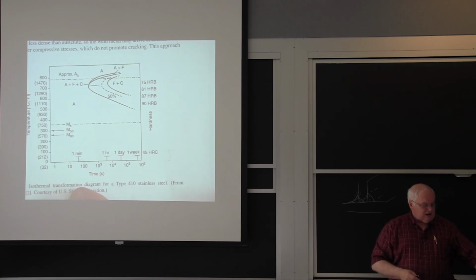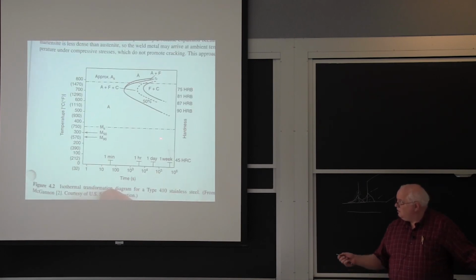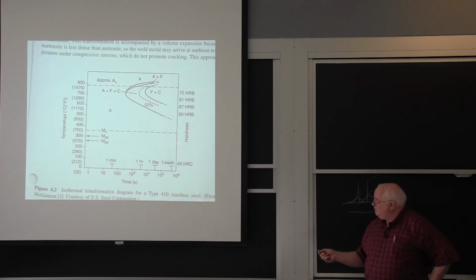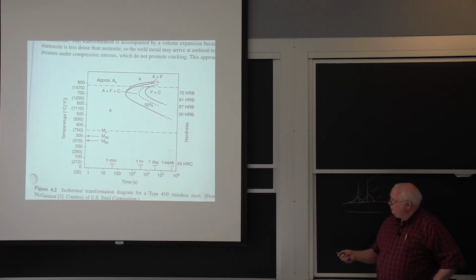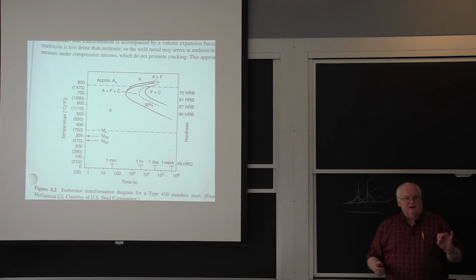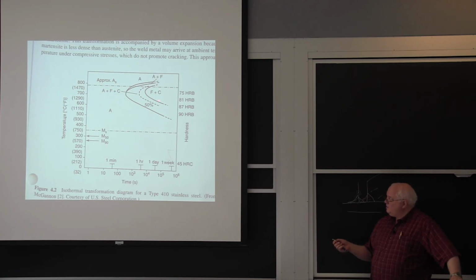There are the ferritic stainless steels, and basically this is the CCT curve for a 410 stainless, which is like 12% chrome. And remember, I was telling you on carbon steels, you had to get past this nose within like 1 second to be able to get martensite and avoid having the austenite transform to ferrite. If you wanted to get martensite, you had to quench it very quickly. Well, you go to a 410 stainless, and now instead of the nose being over here on the log scale at 1 second, the nose here is now at 1 hour.